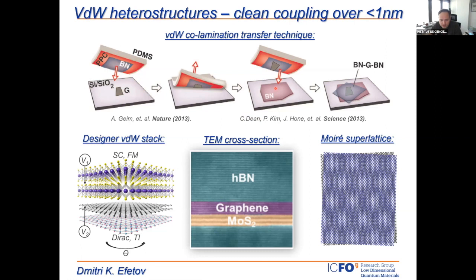The surprise here was that the interfaces formed by this rather rude technique were still extremely good. If you look at typical transmission electron microscopy images of hexagonal boron nitride, graphene, and MoS2, you see that the interfaces are extremely good. What is also very special is that you can align the crystallographic orientations between the different layers, and you can form these so-called moiré superlattices, which I will talk about in a second.